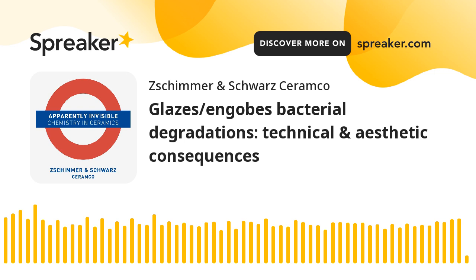The most important are surely linked to difficulty in keeping the glaze in suspension. This means that solid particles tend to agglomerate and to be improperly suspended within the solvent, usually precipitating and developing sedimentation phenomena. Then we can talk about lack of cohesion. This problem arises when glaze particles seem to be unbound and not very, we could say, compact. And these conditions are, of course, not suitable for the proper discharge of the suspension on the surface of the tile.